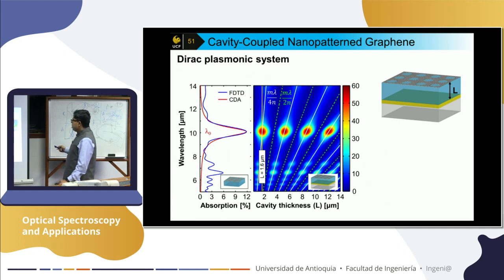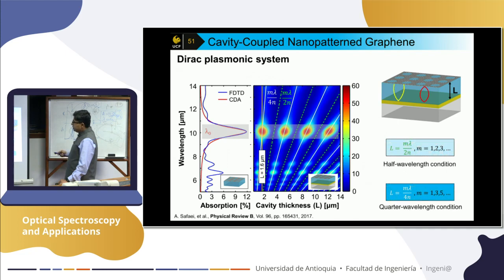Next, we added an optical cavity, and if we control the cavity phase through the thickness or refractive index, we showed that as soon as phase matching happens, we see a strong 60% absorption. When you make a constructive interference in the cavity versus a destructive interference, with constructive interference you excite the plasmon more strongly. So we started from 2% absorption in graphene, but now we can go to 60% absorption without adding any gold or any other material on top.